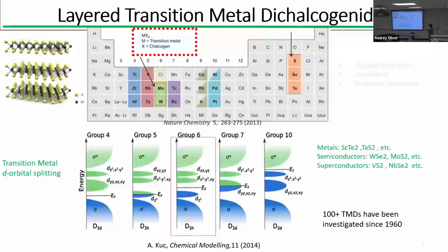So here we have molybdenum and tungsten in group 6, and here are sulfur, selenium, and tellurium. They will have this kind of band structure, right? If your combination is different, you can see how this d orbital splitting happens. We call this crystal field splitting, right? So here you can see there is a gap, semiconducting, and it's metallic here, semiconducting here, metallic. So based on that combination, we can have metal, semiconductor, and even some superconducting properties are also